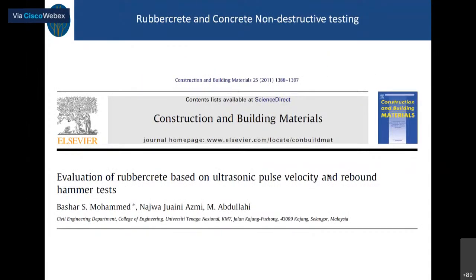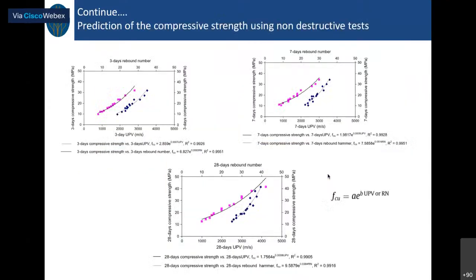And then another paper is the evaluation of rubberized concrete based on ultrasound pulse velocity and rebound hammer tests. When we developed it, we wanted to know how non-destructive tests can be used for this rubbercrete, because usually for concrete the codes are already developed, but for this new material we tested it and found the real curves together with the formula. So if we conduct non-destructive testing on the rubbercrete, we can use these curves to find the real values, and these curves are also available in our publications online. If you like, I can also send it to you.